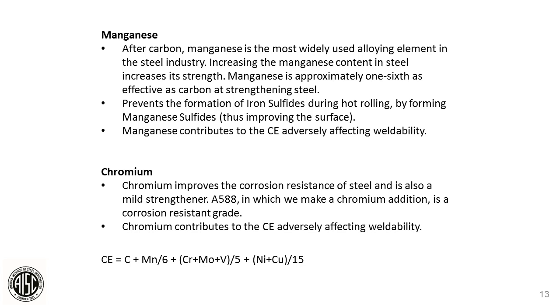So we look at those alloying elements and try to balance strength and weldability and ductility and all that. Of course, heat-affected zone cracking is also affected by the cooling rate of the steel, the preheat, the filler metal. But for us, primarily, our portion is controlling it by the chemistry of the steel. So as we look at chromium, it improves the corrosion resistance of steel. It's a mild strengthener. You'll see this in A588, which we'll discuss in a little bit. And it's a negative effect to the weldability. So on the next slide, please.